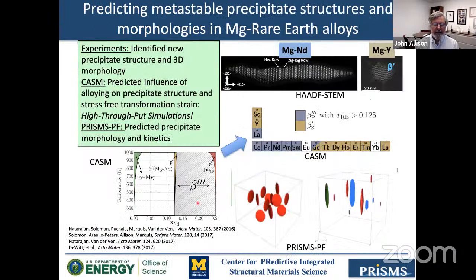And so that led us to propose this as the phase diagram for these neodymium type alloys. So it's basically a continuous sweep of different types of beta triple prime across the entire composition domain from sort of 0.15 in this case to 0.25. So we've identified this new, and we think consistent, phase, if you will, and its 3D morphology.